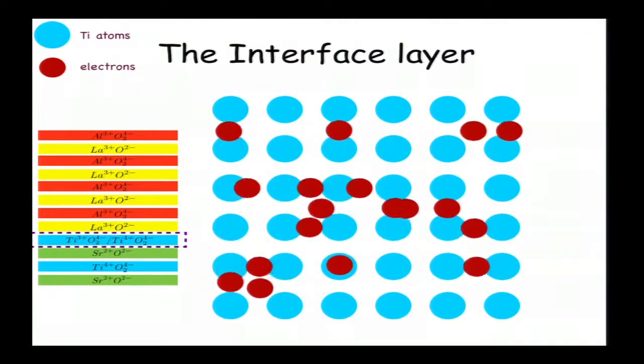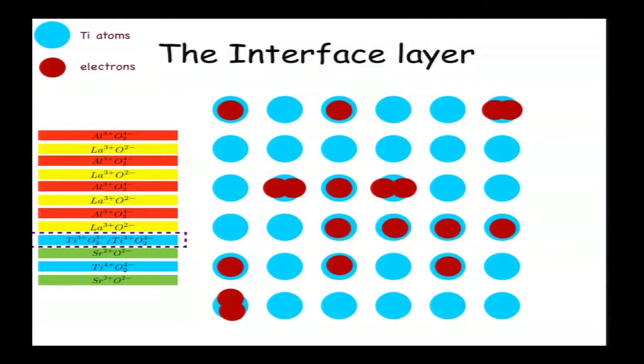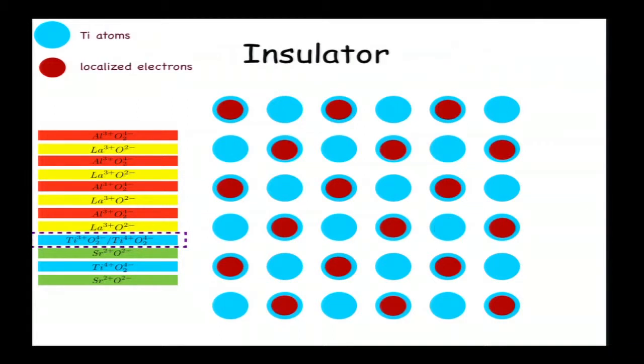But if we, for a moment, freeze our electrons, we can see that at any given moment, we'd expect many electrons to sit at the same atom. But electrons have charge, and therefore they don't wish to sit too close to each other. They repel each other. And if this repulsion is large enough, they want to sit as far as possible from each other. That can be achieved if we don't let them move, and instead localize them on every second titanium atom. Therefore, in that case, our electrons are not going to conduct. They are going to be an insulator. When a measurement of conductivity is done, these electrons are not going to participate. And that's why we don't see most of the electrons when conductivity is measured.